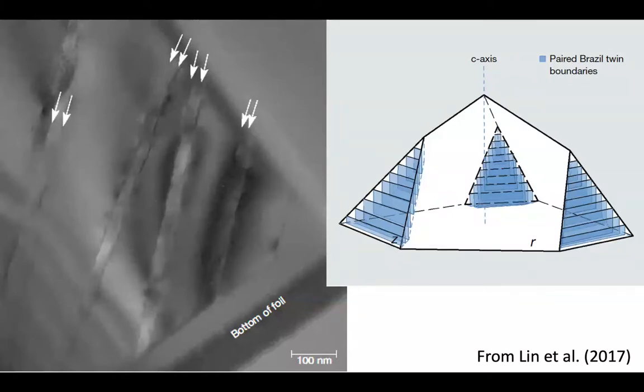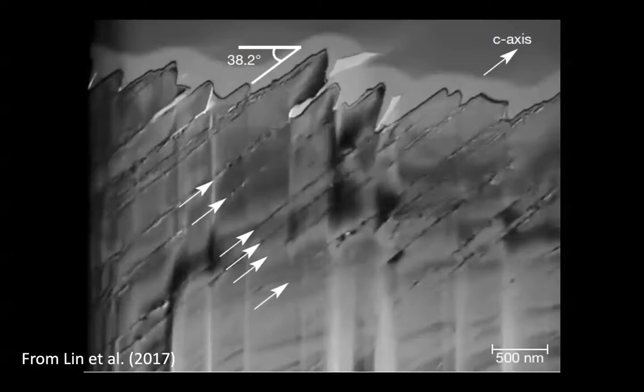and twin that boundary. So what we observed then is that in these Z faces of the quartz crystals that are iridescent, there are these polysynthetic Brazil twins that are lined up with a periodicity that's exactly right for the diffraction or scattering of visible light. Now, there has to be a final stage here, because C.V. Raman himself was thinking maybe Brazil twinning is possible here. But the problem is that Brazil twins themselves are not going to lead to iridescent effects because they have the same refraction index. You have to do something that's going to make the light kind of reflect.